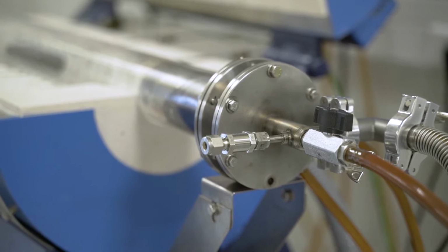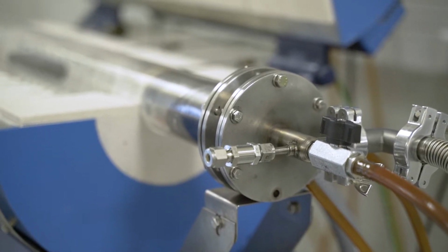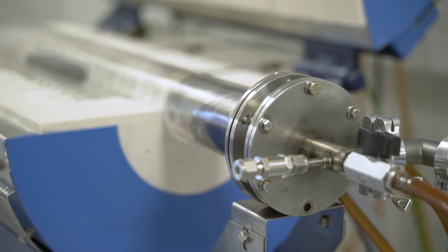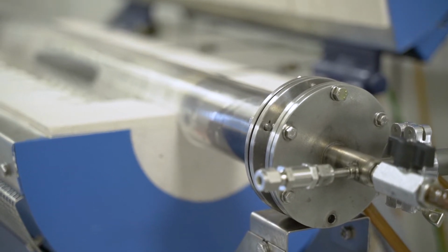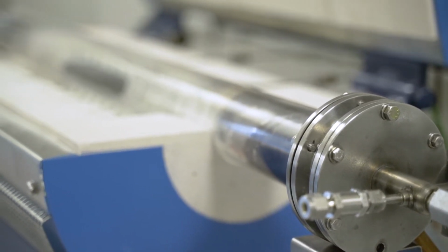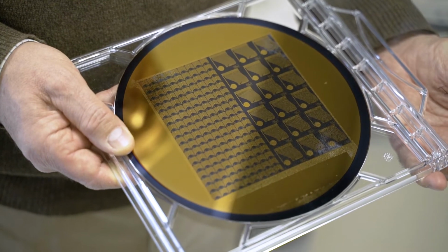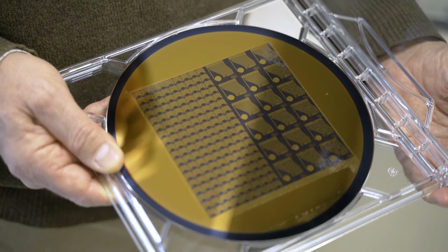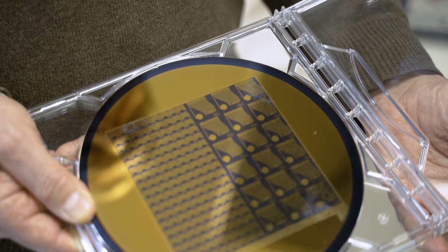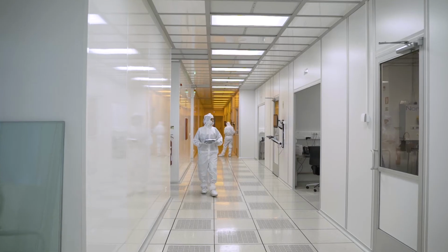Graphene is grown in a chemical vapor deposition system, not very different from this one, where we use a copper foil as a catalyst for growth. And then it is transferred using a temporary polymeric substrate onto the final wafer, where we then fabricate the devices. Understanding how the device works theoretically will help us to improve the quality of the device and find even more applications, like bio and molecular sensing.